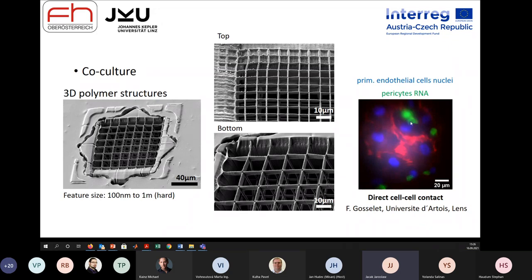We stained the RNA, and we incubated for several hours. Unfortunately, they do not survive this staining for a long time because RNA is blocked, and so some processes are not so efficient and they don't feel well. But for imaging, it was fine. And you see that these are the parts of cells that you can see, and they came from the bottom. So you see cells here. Of course, these are also the nuclei of the cells where the RNA abundance is highest, that came from the bottom and interact with the top layer. The top layer, in order to get it so tight, is not a matter of hours, it's a matter of days. So they were cultivated under flow conditions for 5 days prior to the adding of the second cell type.